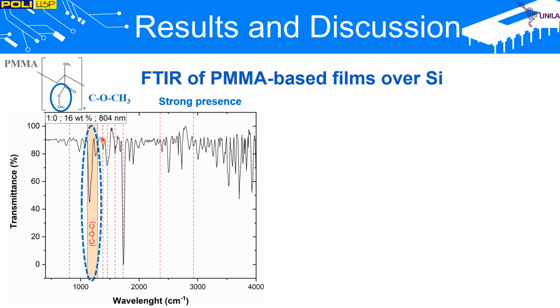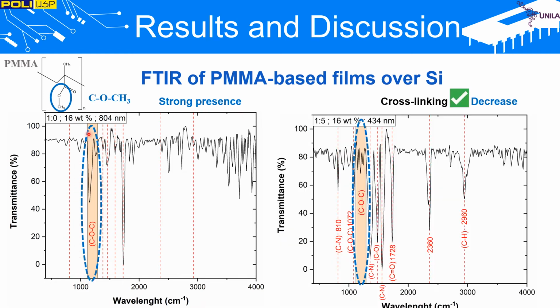Similar results can be observed for PMMA films. In the FTIR spectrum of PMMA without PMF, a strong presence of COCH3 bands can be seen. We can affirm that the cross-linking between PMMA and PMF exists when these COCH3 bands decrease when PMF is added. In the opposite trend, there was an increase in bands related to the triazine ring attributed to CN groups directly attached to it.